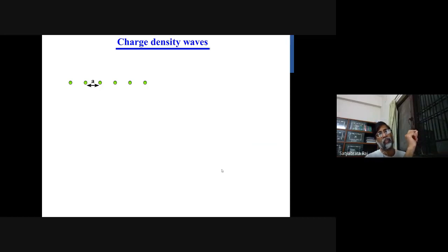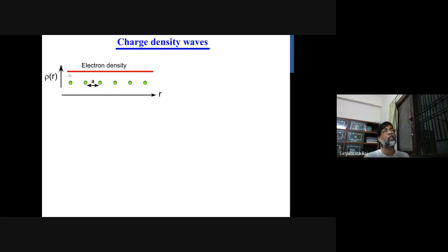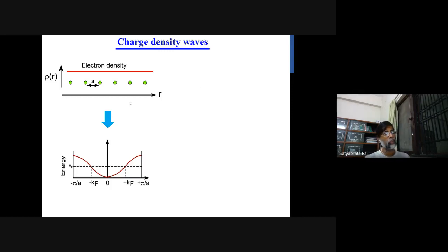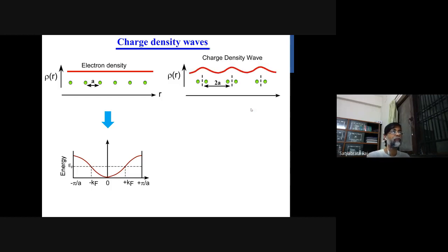Let's take a chain separated by A, and if you lower the temperature, your density of states is quite flat. If you plot your band structure, you have a parabolic band, and let's assume you have a KF point here, with the band crossing at the EF. Now, because of lowering the temperature, there is a competition between the electronic energy and your crystal lattice energy, and to stabilize it, one lattice point will move towards another and make a two-fold periodicity. Then your density of states, or the charge density, becomes a wave. That is why it is called a charge density wave.